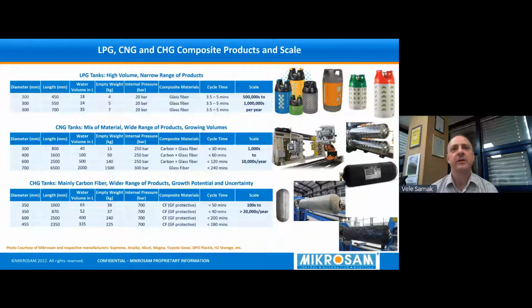Low pressure, mainly glass fiber, and short cycle times, less than 5 minutes, and you can get down to even lower as you scale that operation. So not a lot of product variability, but huge volumes and short cycle times.